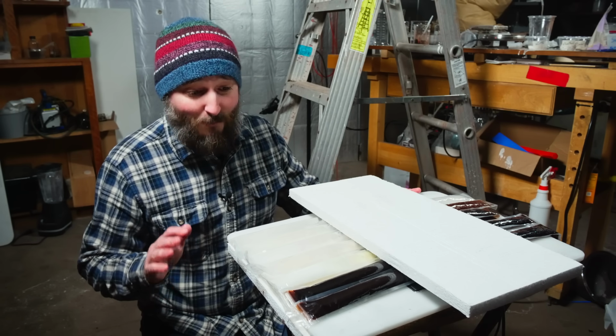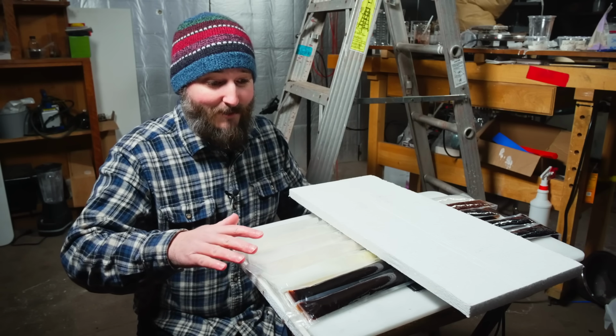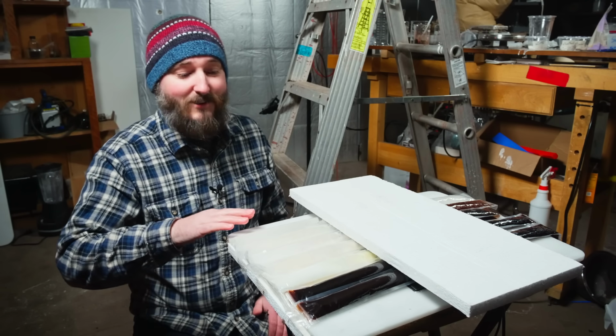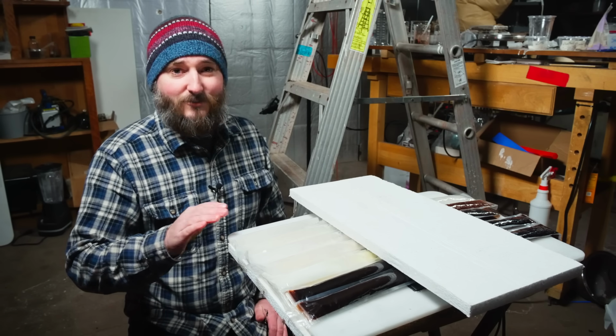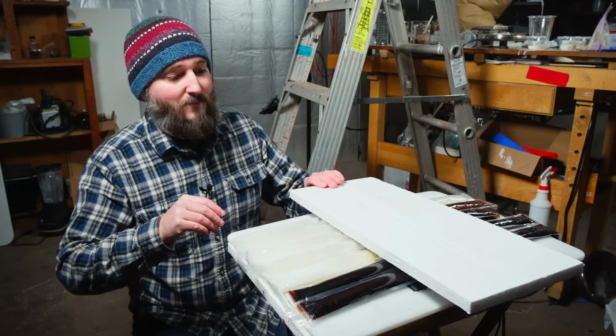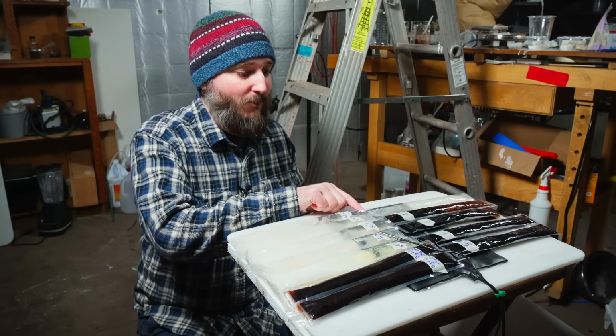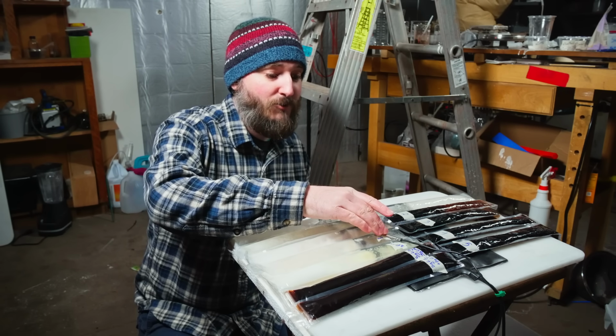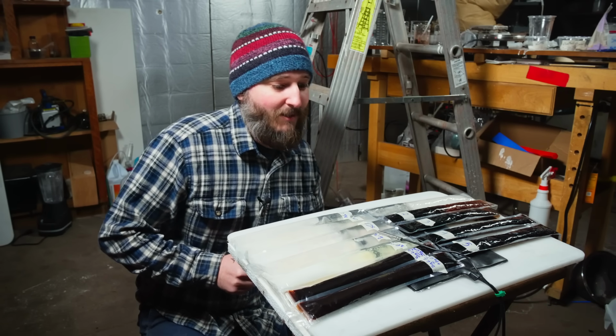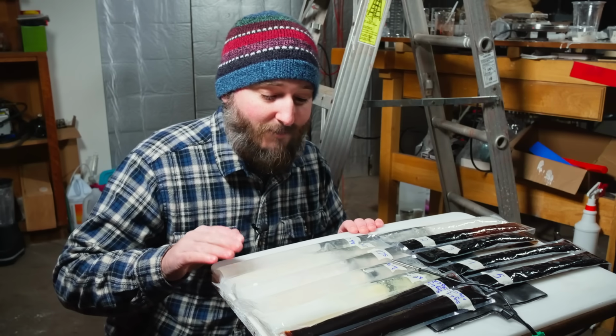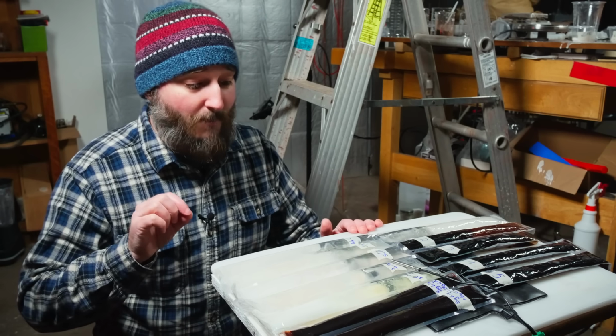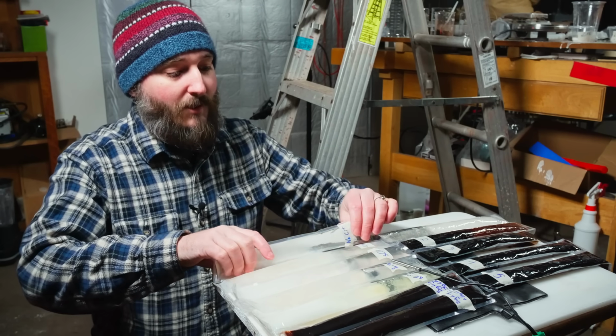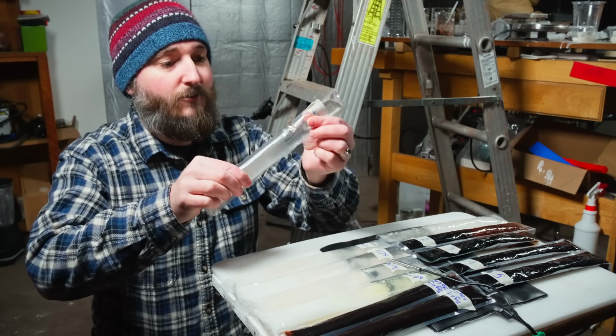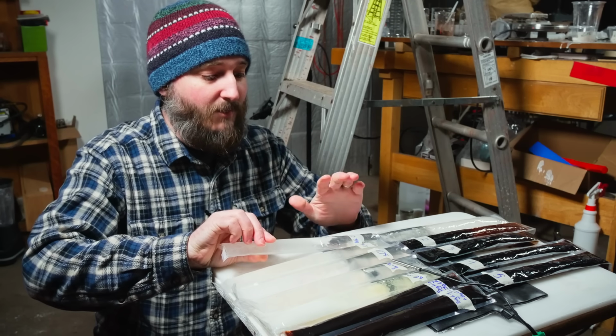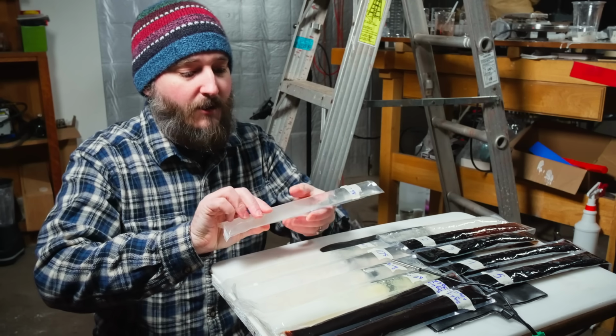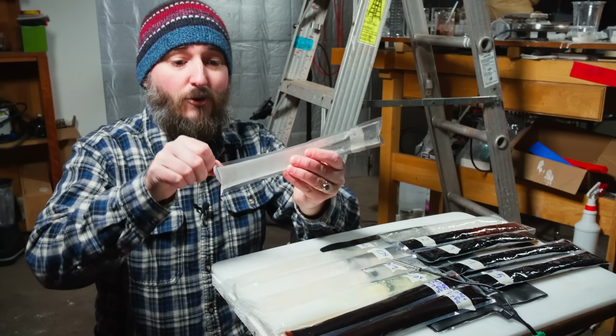Since I've been inside for like 4 days, this test has had plenty of time to make these samples go through many hundreds of thermal cycles, just from the fluctuations in the room temperature and from the reptile heating pad, which is below these samples, cycling on and off to maintain its temperature, which was set to 100 degrees Fahrenheit. So what I'm looking for in the results is for any hard monocrystalline formations at the boundary layer between the molten section. So we have a molten section of the tube, which was what was on the reptile heating pad maintaining a warm temperature. And then we have the frozen section, which was overhanging the edge.